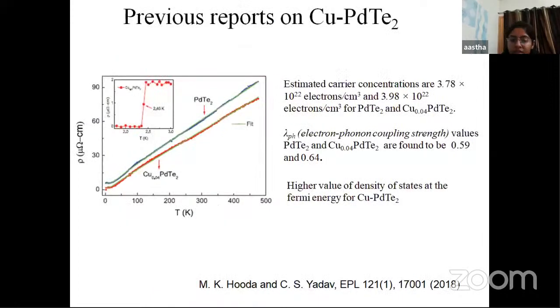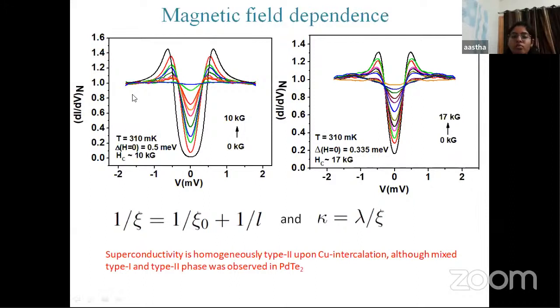So we also did magnetic field dependence on various spectra that we observed at different locations on the surface of PdTe2. Although the critical field was found to be different in every case, it was indeed higher than in pure PdTe2, but it was different at different positions. The one thing that was common is the observation of homogeneous type 2 superconducting behavior upon copper intercalation, which was expected.